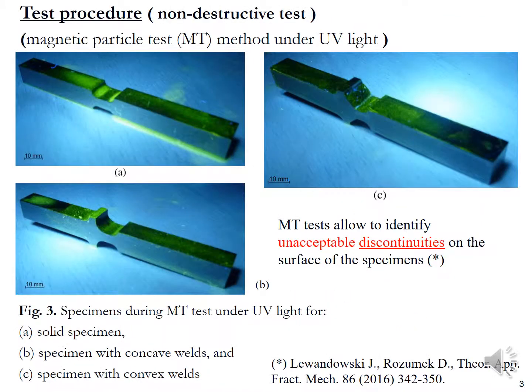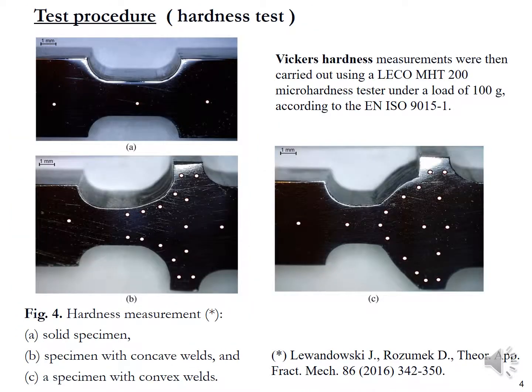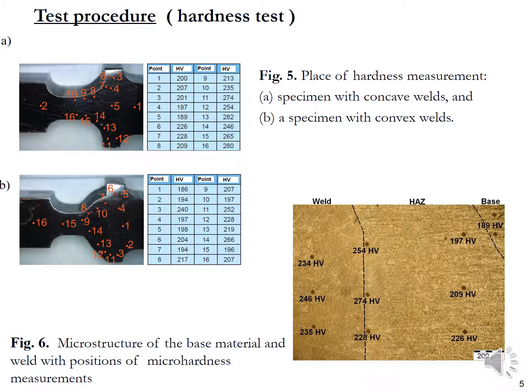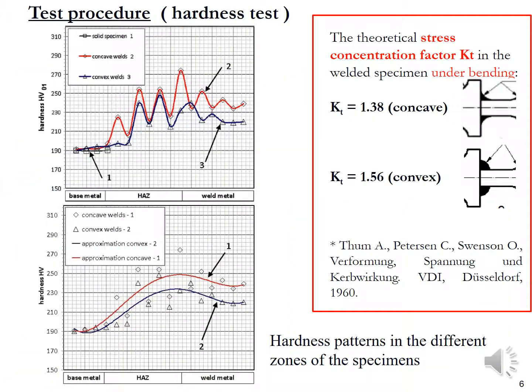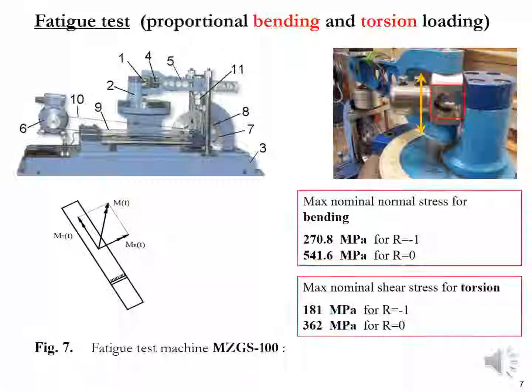Magnetic particle test method under UV light has also been used prior to testing. Furthermore, the hardness in the welded area and in its surroundings has been measured. The map of the hardness has been obtained for all the three types of joints. The highest hardness is reached in the heat affected region, while the lowest values are located in the base material. The theoretical bending stress concentration factor has also been determined.